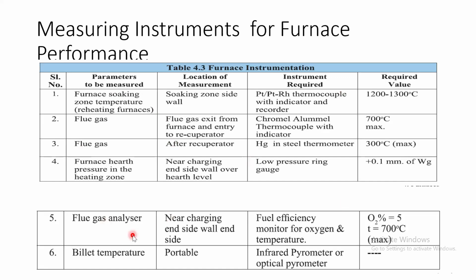Next is flue gas analysis, which has to be done near the charging side inside wall, where the flue gas goes away to the environment. The instrument required is a flue gas analyzer or fuel efficiency monitor for oxygen and temperature. The required value is O2 percent equal to 5. Already I told you that oxygen percent for best combustion should be around 3 to 5%. The same thing is mentioned over here. The temperature of the furnace at exit is around 700 degrees centigrade. So this is flue gas analysis.